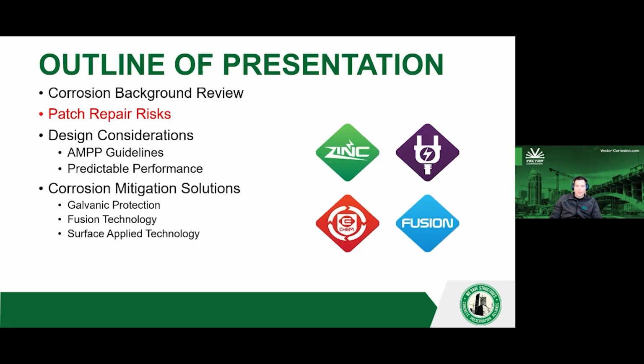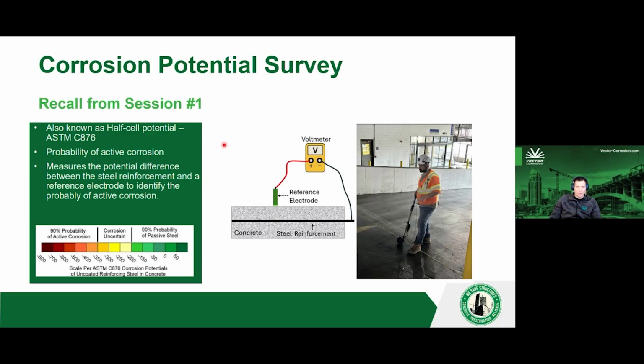Now I'm going to move on to some risks of patch repair. And again, I need to recall from session one, there is a non-destructive test method, or rightly maybe a semi-destructive test method, called the half-cell potential survey. It gives you the probability of active corrosion in a structure without having to physically see it. So you need to take a multimeter or a voltmeter, attach one lead to the steel in question of your structure, the other lead to a reference electrode, and you can read off a value. And the values can tell you the probability of active corrosion going on. So with a copper-copper sulfate half cell, any number more negative than minus 350 indicates you're in an area of active corrosion. Probabilistically, anything more positive than minus 200 indicates you're very, very likely in an area of passivity. This is a very powerful technique to give you a picture of what's going on in your structure.